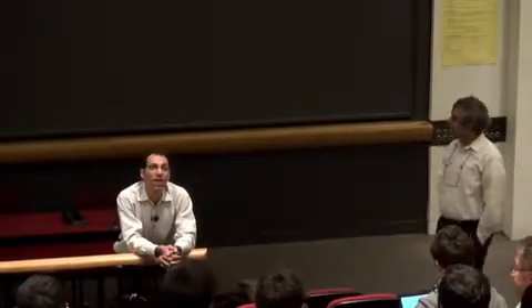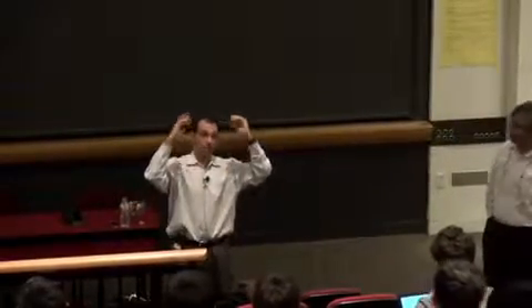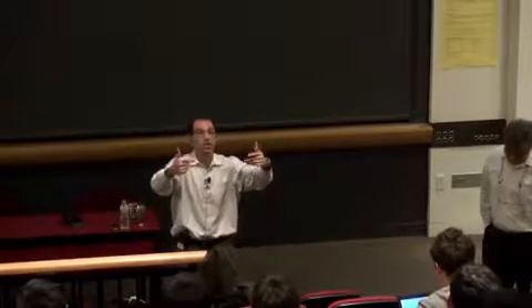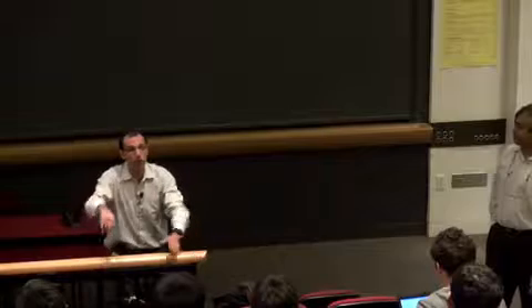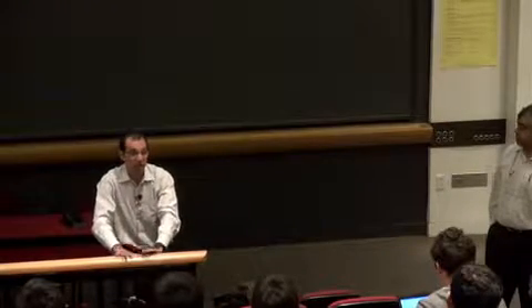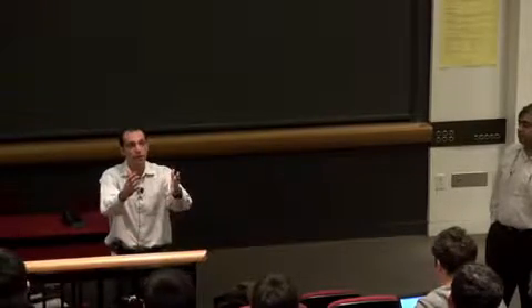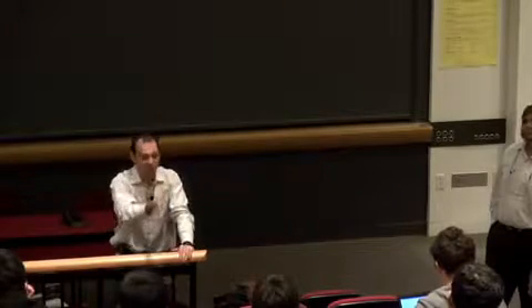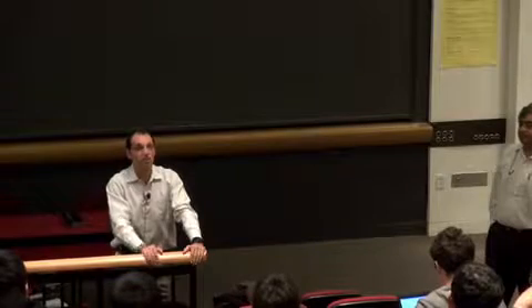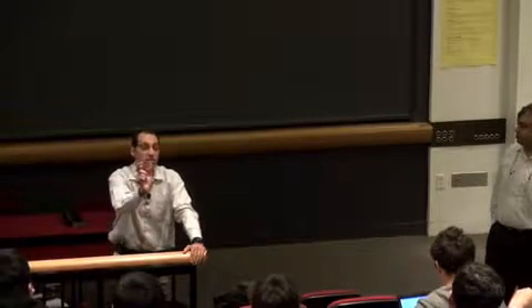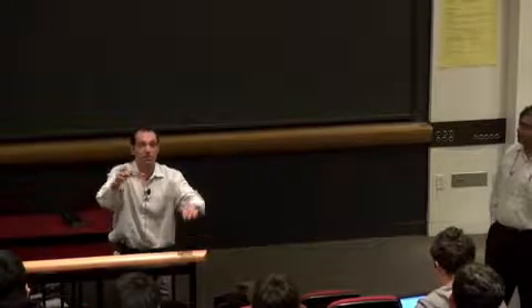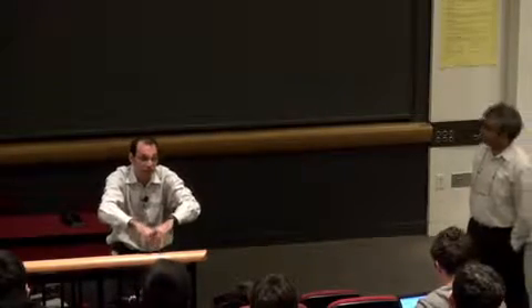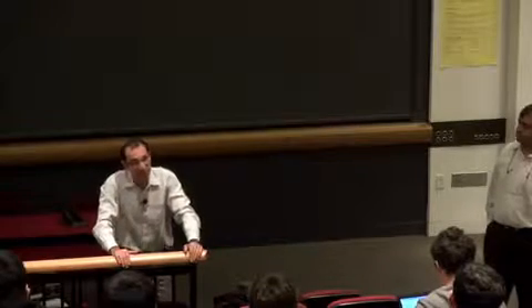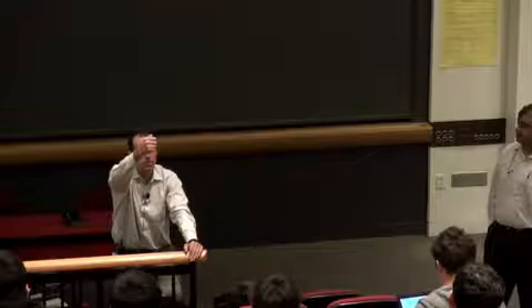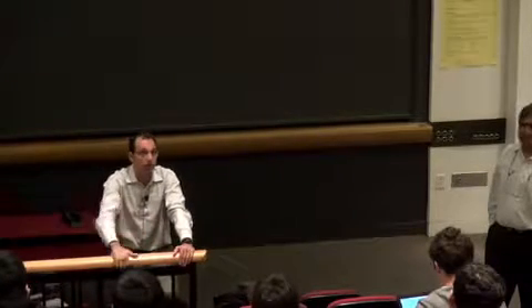What do you see along this chain, actually, along the edges? Do you still see the gap? Yeah, no. So what happens is you induce a gap. If you do the experiment, like the chains we have built so far, you see a gap in the middle, which is somewhat changed from that of the bulk, but it looks reduced. So what you're looking for is a gap that basically is of a different superconducting order parameter, and the model calculation shows it. Experimentally, we do see a clear gap in the middle of the wire and no clear gap at the ends, but there's much more experiment that needs to be done. The model shows it clearly: when your zero bias state appears, it lives in the middle of a gap. But this is true of all these models that produce the Majoranas.